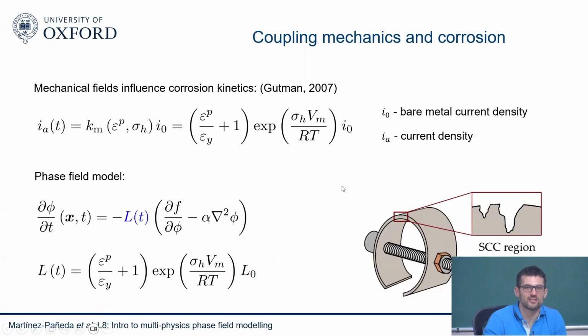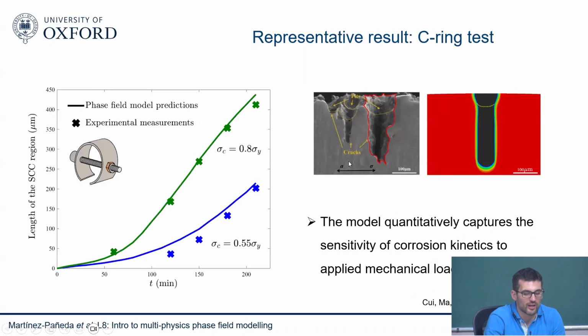So this C-ring test is a test where you have a bolt or a screw, and then you just tighten that screw and basically consider different load conditions. So it's a constant load, but you can play around and see different loading configurations. And you can measure here at the top what is the growth of the stress corrosion cracking region. So this is what you get from the experiments. The symbols are the experiments, and the lines are the predictions of the model.